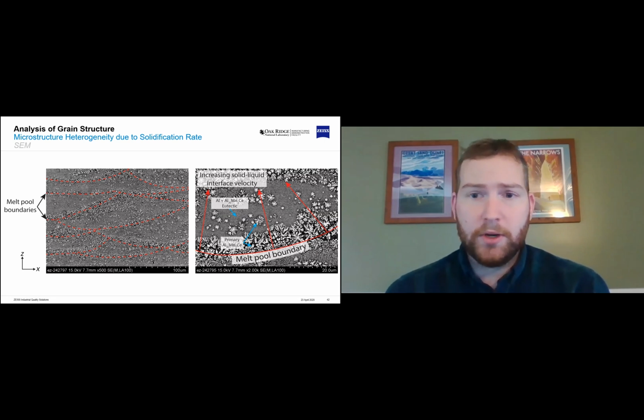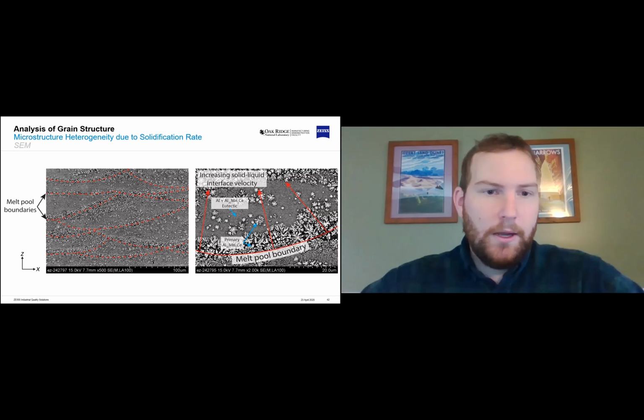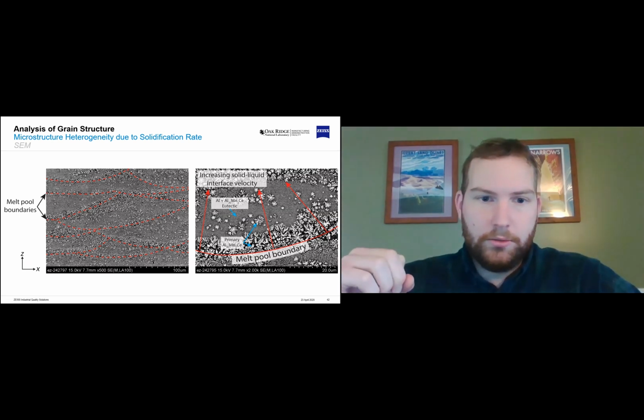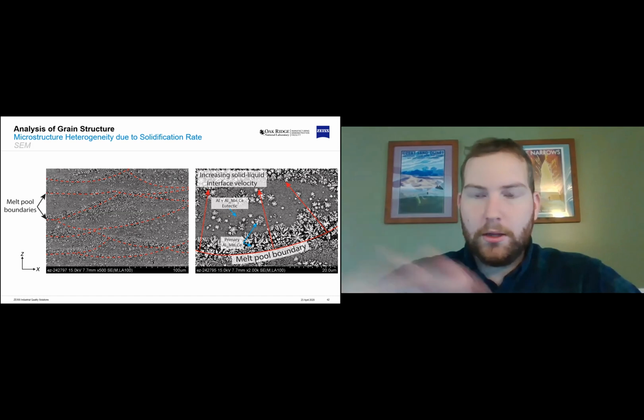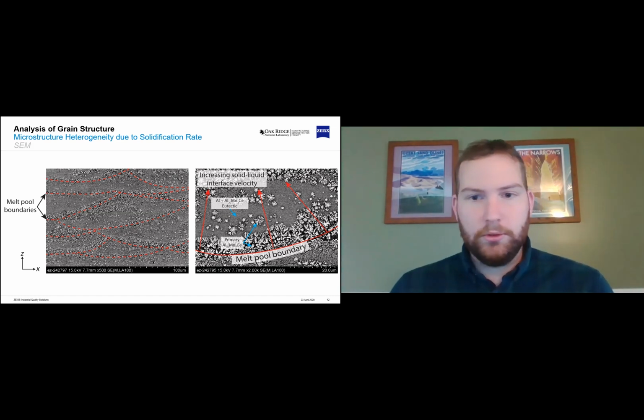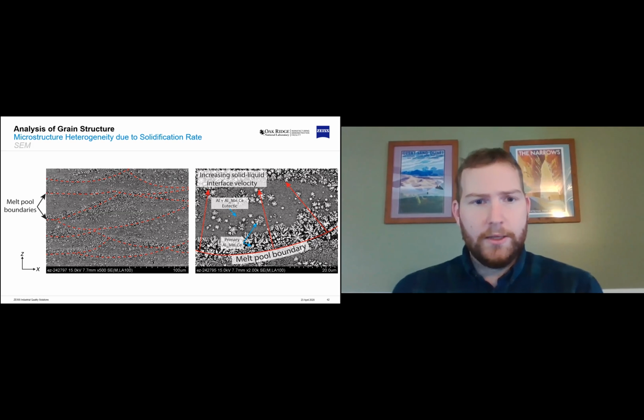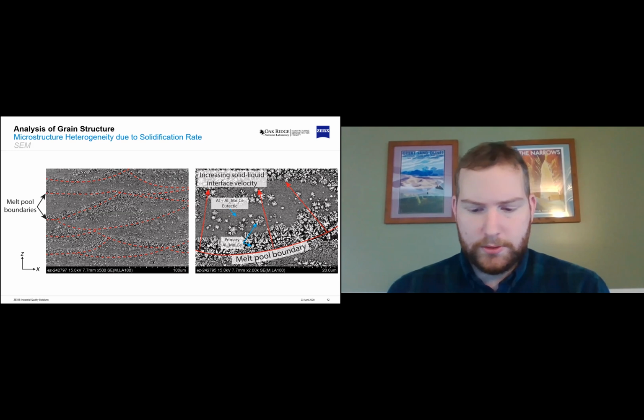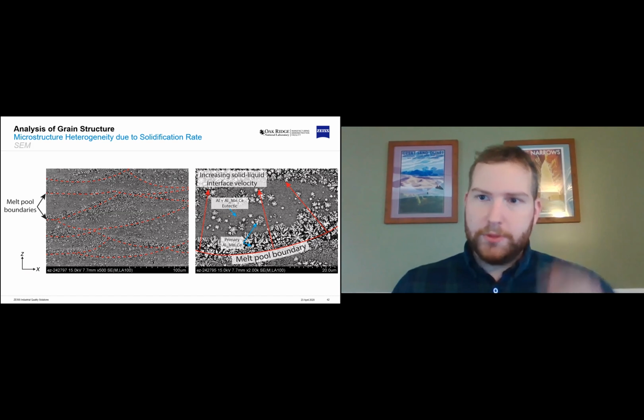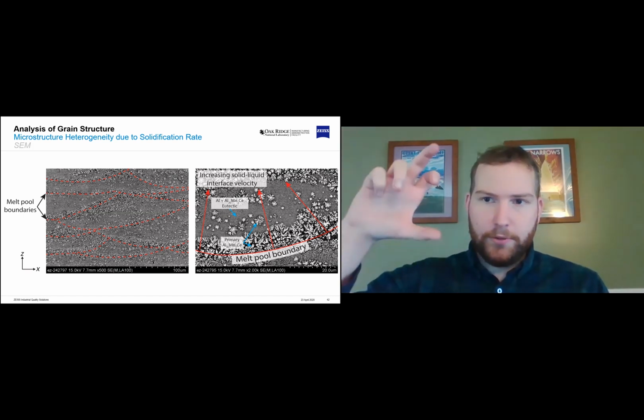And it's been a challenge for us to get good images on these kinds of things. Specifically when we're trying to do large area EBSD, when the grains are so tiny, then you really have to be tight with your brightness and contrast and your signal to do a mosaic across these sections, or else you'll lose the entire image. And so one of the things that we did with the blade project, I don't think I have an image of it either. The blade has a couple different components to it. There's a fir tree at the bottom, then there's the airfoil, and then there's a shroud at the top.